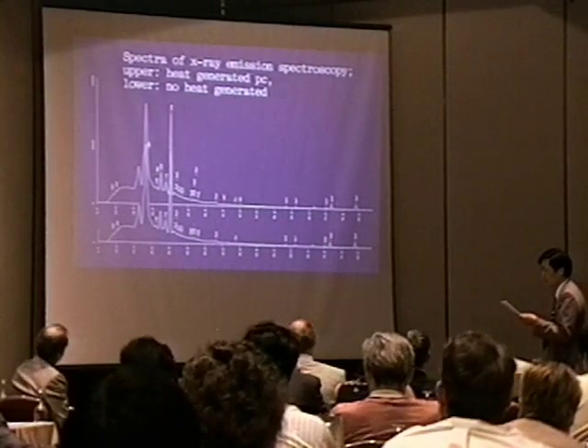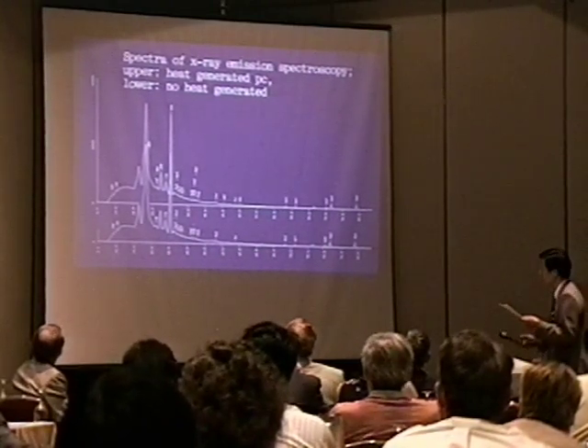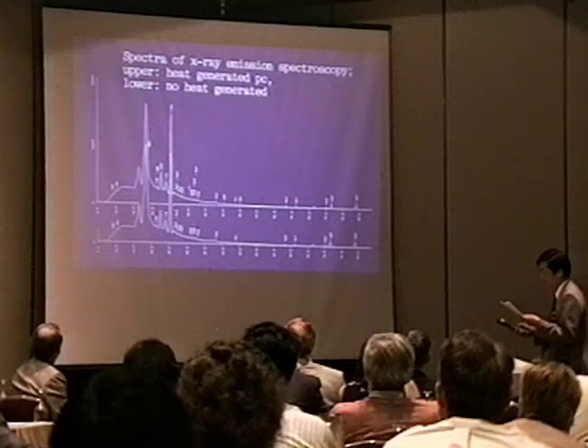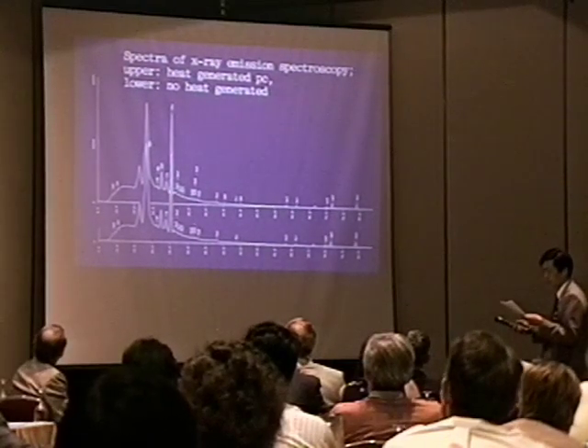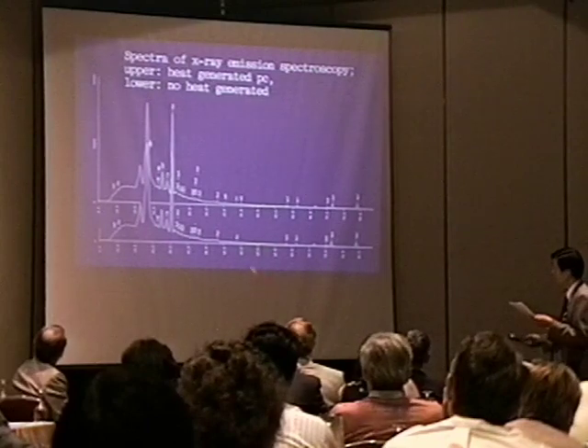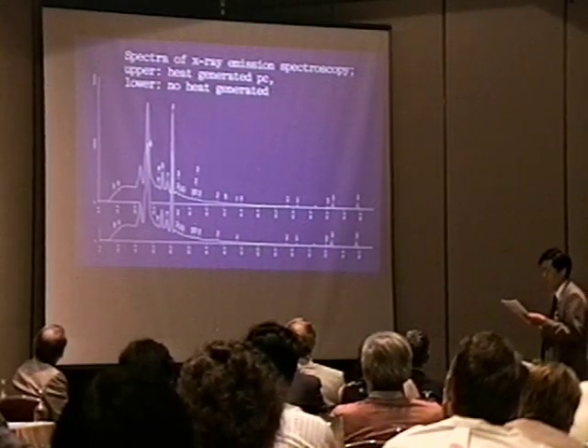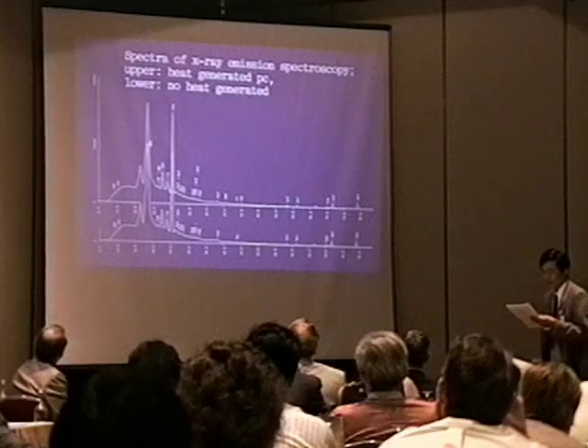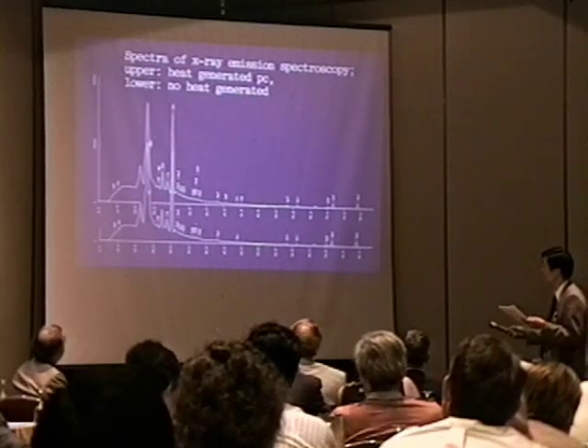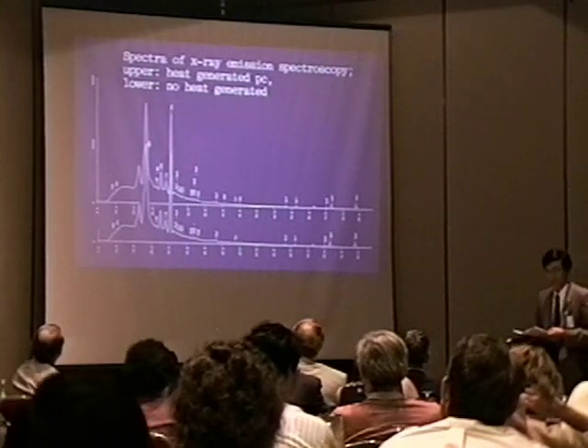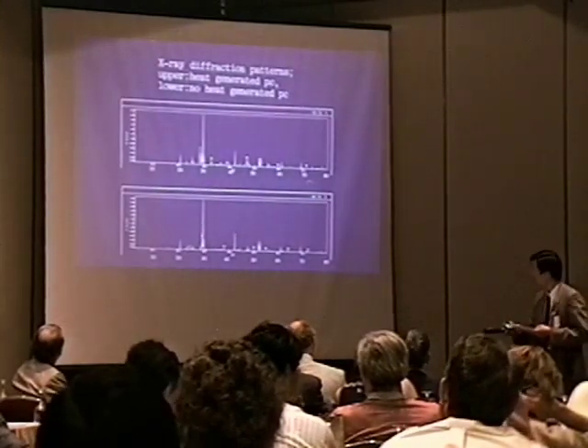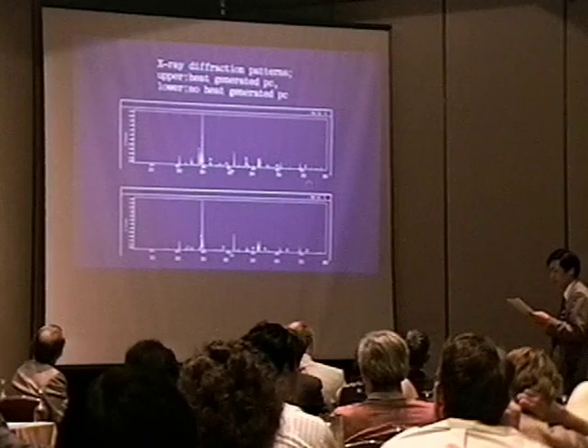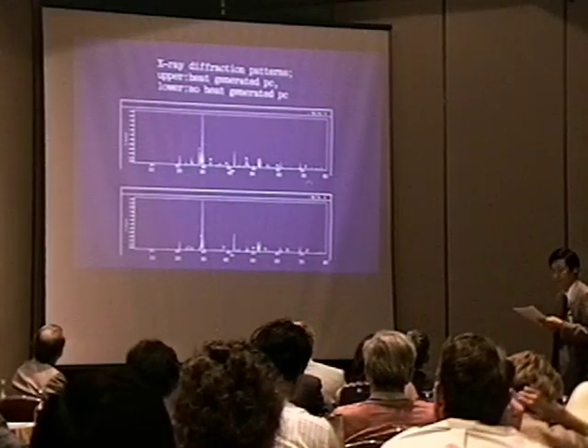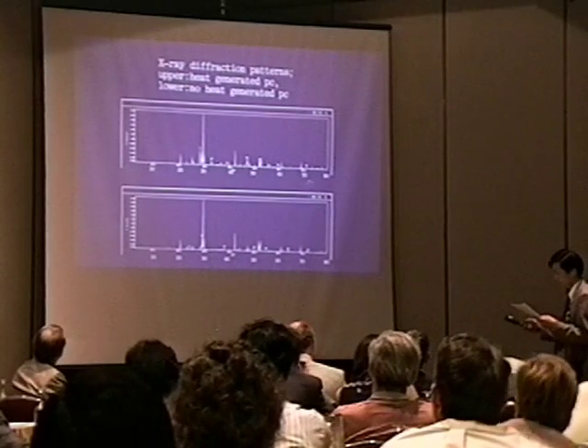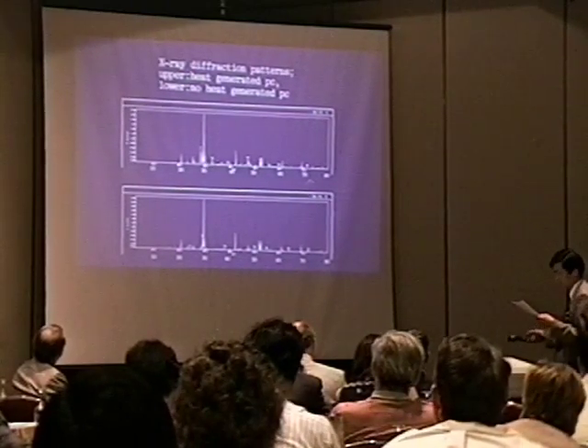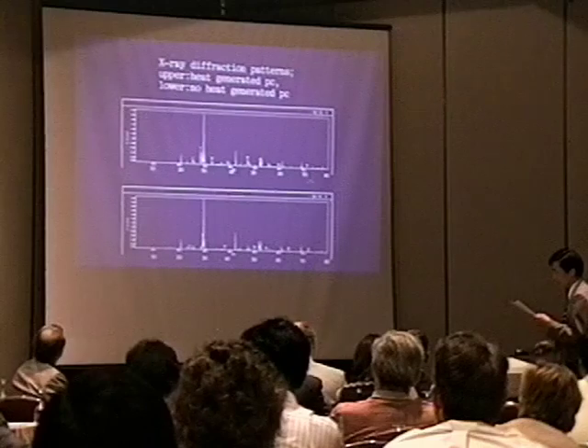This shows spectra of the X-ray emission spectroscopy. The upper spectrum is for the sample which generated heat. The lower one is for the no heat evolved sample. No difference was noted between these spectra. Next slide, please. These show the difference of diffraction spectra between heat evolved and no heat evolved samples. We can see some differences between them.